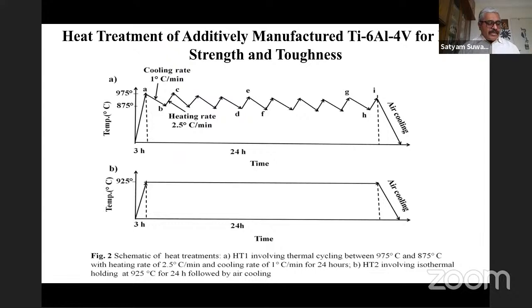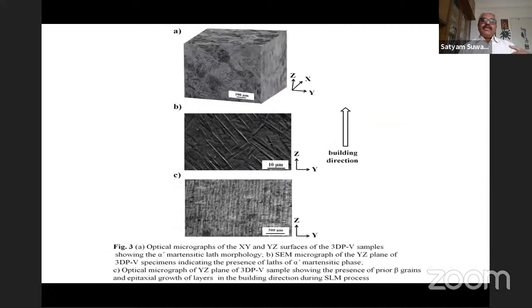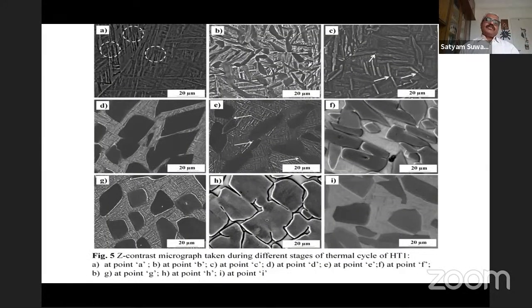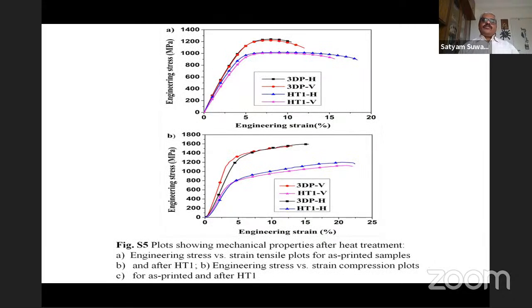Heat treatment, just in a few minutes, I will tell how the heat treatments are important, even for Ti-6-4, which is another material which is used in the cold section of aero engine components. So there also heat treatments are to be suitably designed. We have done it, and we have seen that a specially designed heat treatment leads to an equiaxed microstructure, because as such, because of very fast cooling rates, we get a martensitic structure, which has to be converted into an equiaxed structure, and that requires a very subtle kind of specially designed heat treatment. That gives lots of opportunities for metallurgists to play around with